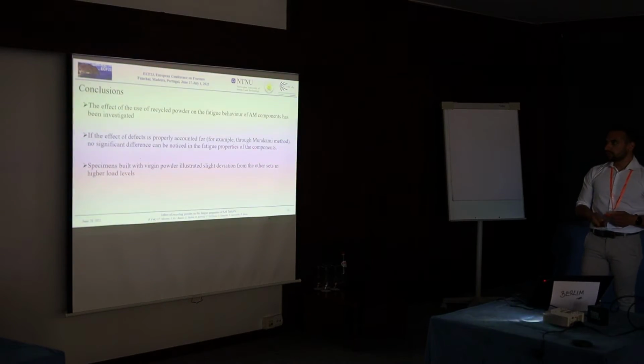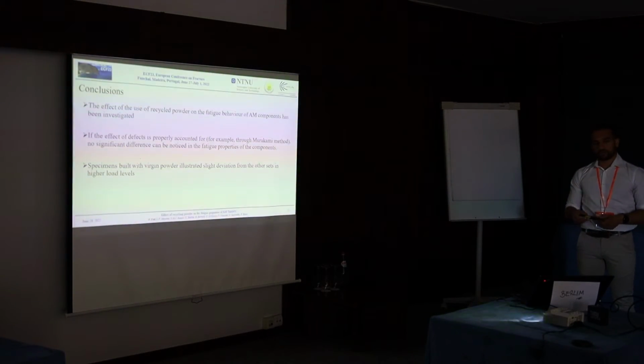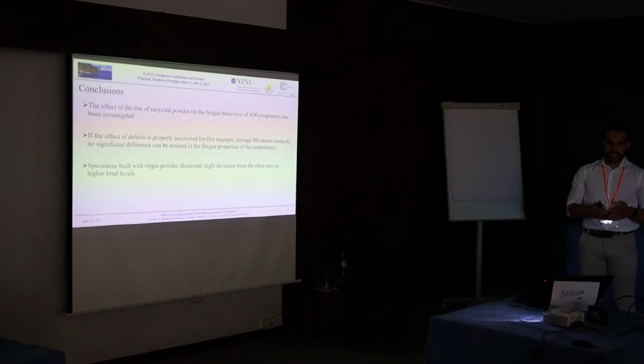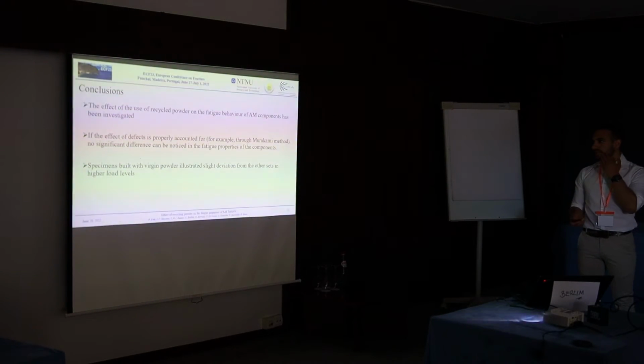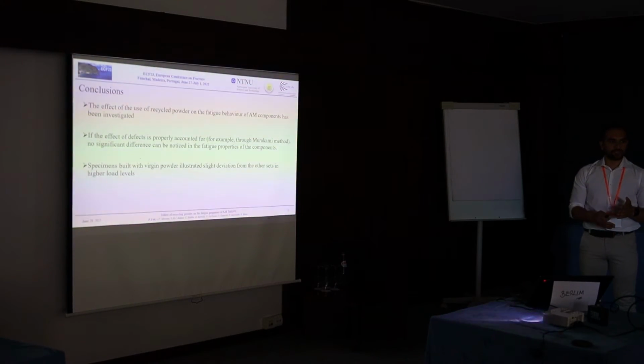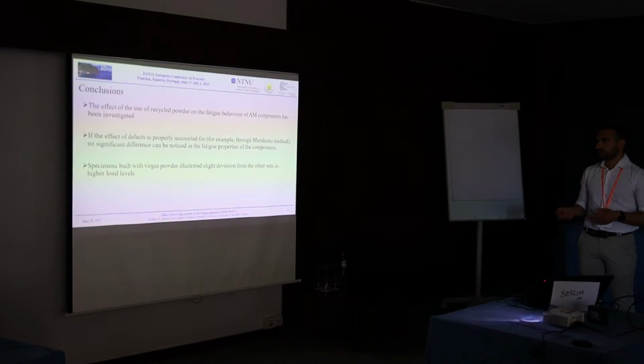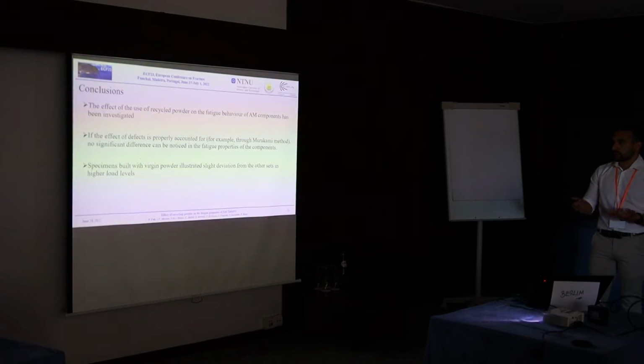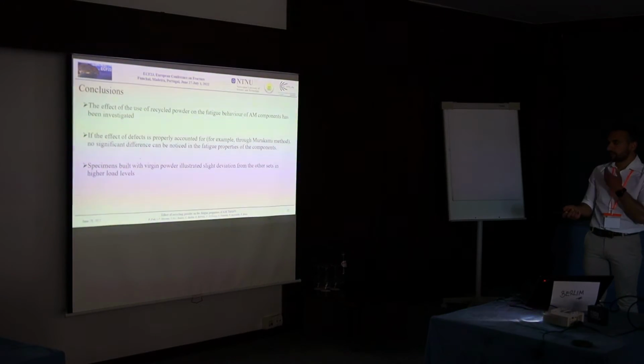So, the conclusion of this work is that the effect of the use of recycled powder on the fatigue behavior of additive manufacturing components has been investigated. And the main conclusion is that if the effect of the defects is explicitly accounted for, such as through a method like the Murakami method, we have not noticed a significant difference in the fatigue properties of the component, and in this way we do not expect a difference in the performance of the two different components.